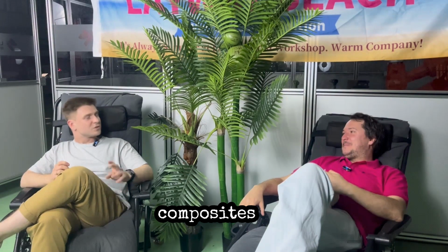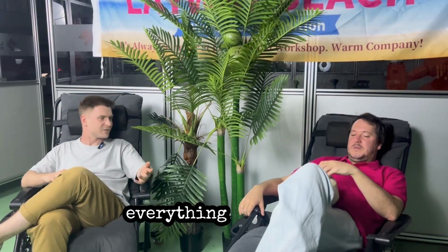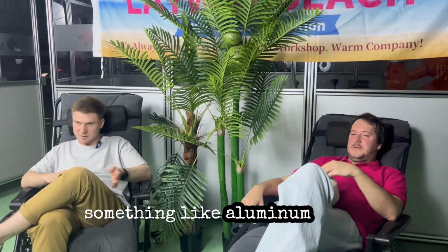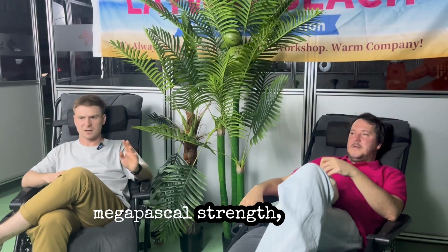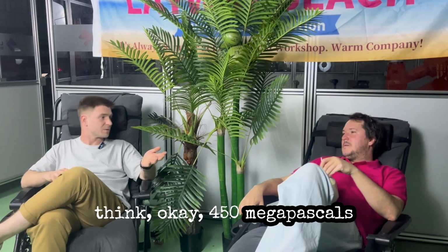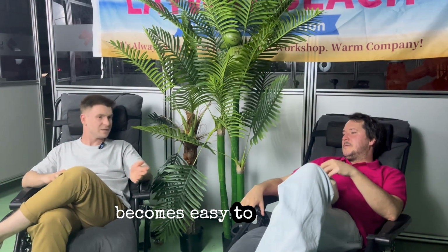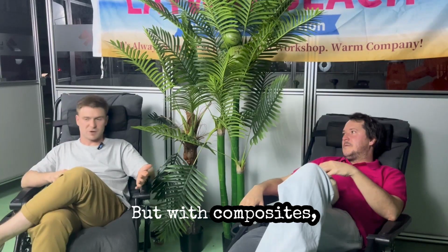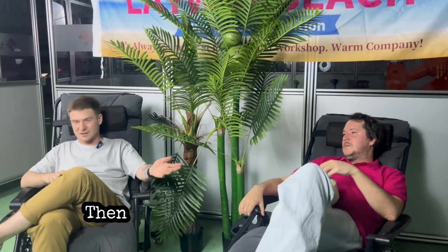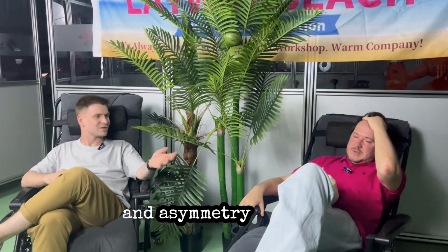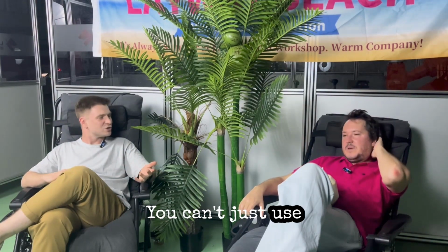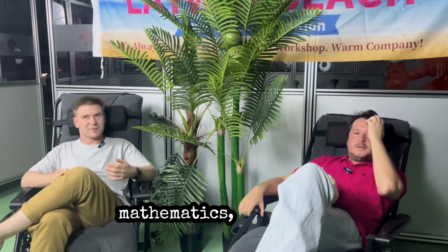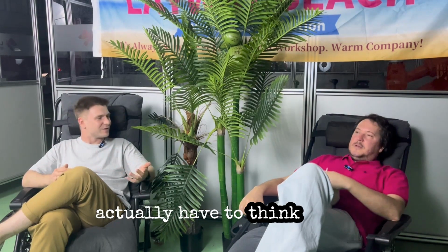I think it's because composites are mechanically more complex. We already said there's Y, X, and Z, 3 axes. With metals, everything is simple. You open a handbook, take something like Aluminum 2024, it has there, I'm afraid to misquote it, but say around 450 megapascal strength, and you think, okay, 450 megapascals in every direction. You calculate equivalent stresses using von Mises, and any structure becomes easy to analyze. Very straightforward. But with composites, we suddenly have different strengths along different axes. Then we have shear properties, different stiffnesses, and asymmetry between tension and compression. You can't just use von Mises anymore, you need more advanced mathematics. And to use more advanced math, you actually have to think hard.